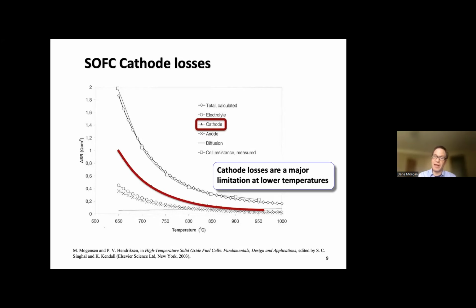And consequently, when you go to lower temperatures, it often becomes a dominant source of resistance for your system. So there's always a lot of interest in trying to develop materials that have a good ability to pull oxygen into them and split the oxygen without having a significant overpotential, which is what gives rise to this increase in the area-specific resistance at lower temperatures.